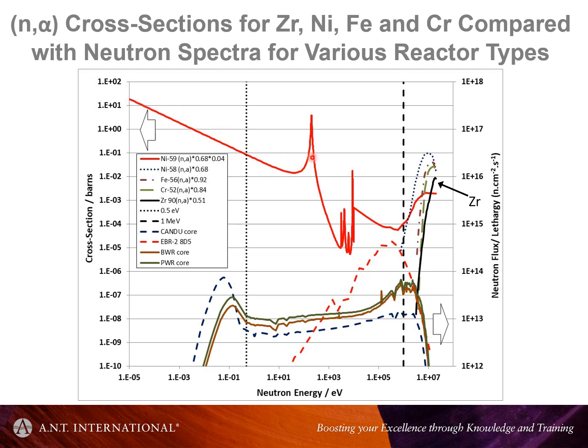And I've actually scaled these cross-sections based on the isotopic abundance. So you can see how even when scaled, if you have nickel-59 around, at the maximum production, at the peak value, the steady state value of the nickel-59, the maximum amount you can get, there is a very high probability of creating helium particles at low energies. So if you have a high thermal energy reactor such as CANDU reactor, watch out.